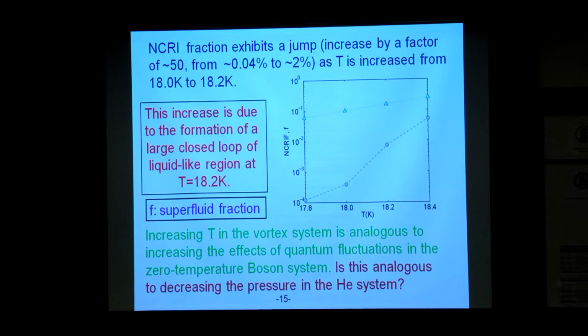Then one would see that the system will, as one changes an appropriate parameter, go from a situation where there is very little or almost no non-classical rotational inertia to a situation where there will be a substantial amount, although the fraction here is still a few percent, which is also what one found in the experiments on helium. One has to understand what increasing T in the vortex system means for the boson system, because the mapping is such that the inverse temperature corresponds to the thickness of the system. So one cannot do experiments by changing the thickness, but one has to think about how one can actually cross this, how one can simulate this in a system, and one way of doing that could be increasing the pressure, etc. So some other parameter that you have in the bosonic system.